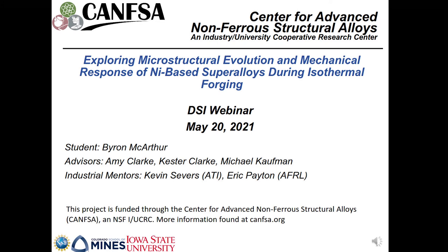The critical stresses for abnormal grain growth to initiate, either dynamically or statically afterwards, are relatively low. They're about 0.15 strain. And so you can do continued deformation afterwards, but the abnormal grain growth conditions are really this early-on condition. And we're doing a compression test as opposed to a tensile test in this situation, so you don't have that final fracture.